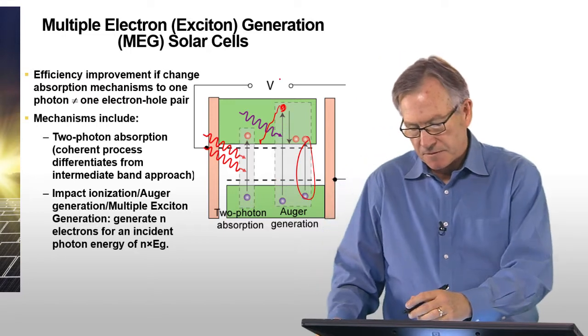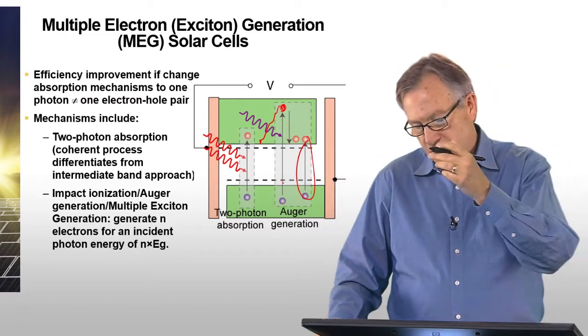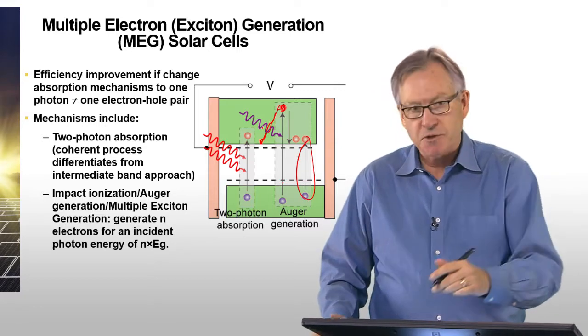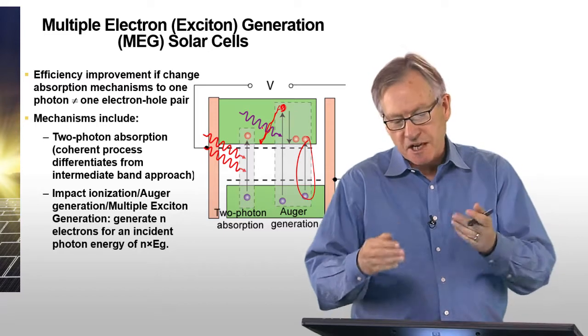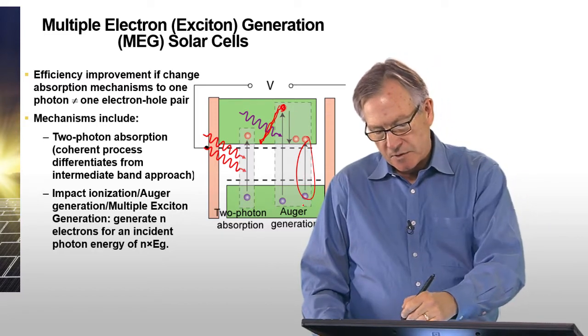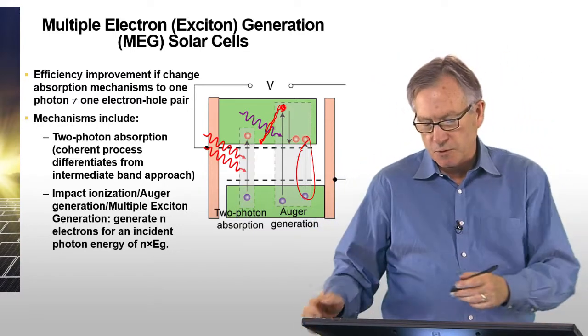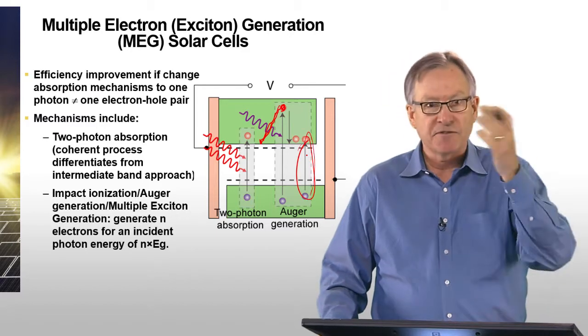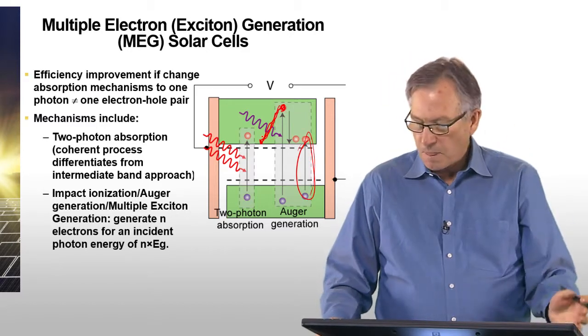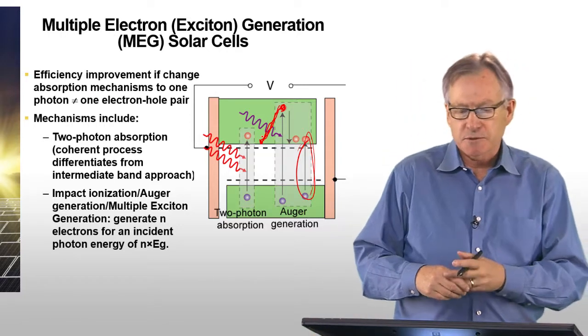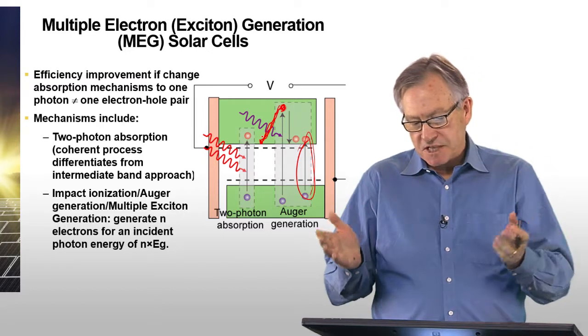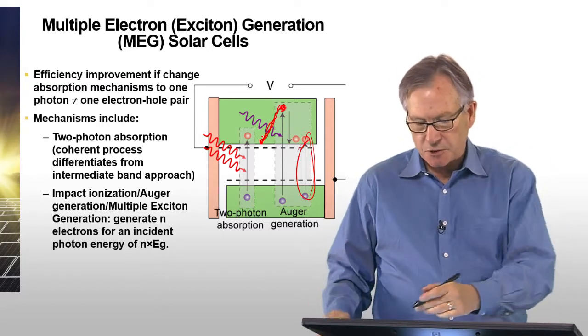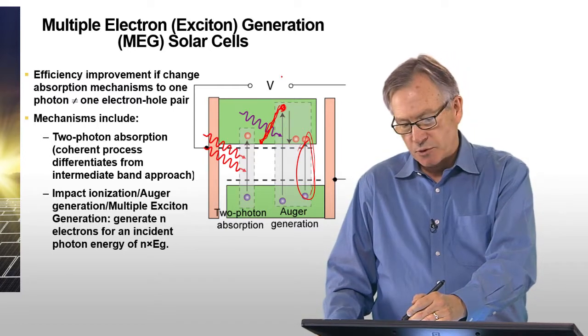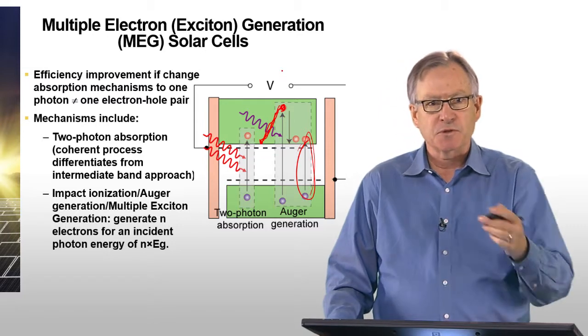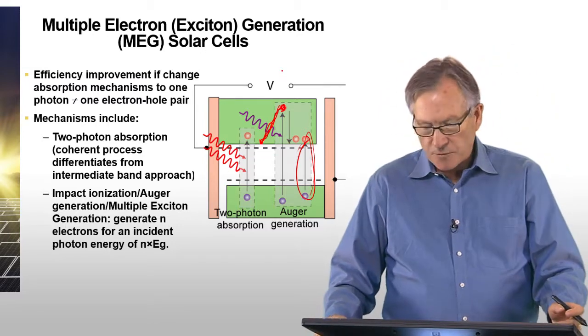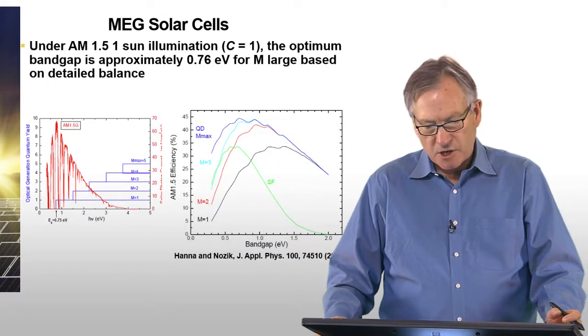So this can only happen if this impact ionization rate is much larger or much faster than the thermal relaxation rate. So there's a competition between the ultra-fast carrier dynamics of energy relaxation and that of impact ionization. You have to have favorable conditions in order for this impact ionization rate to be fast and this process to be slow. Practically speaking, this can't be realized in bulk semiconductors because bulk semiconductors like silicon have to satisfy energy and momentum conservation, and the threshold for this process to occur is pushed up in energy to such a high energy that it's outside of the range of the solar spectrum and practically useless. However, for quantum dots, it turns out to be quite effective, as I'll talk about in a minute.